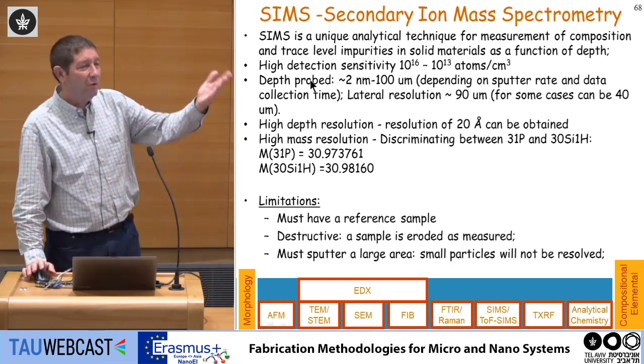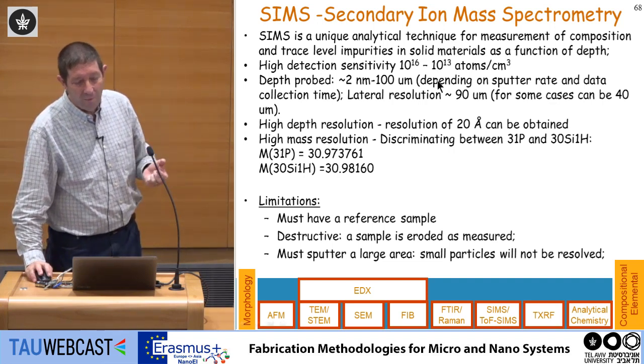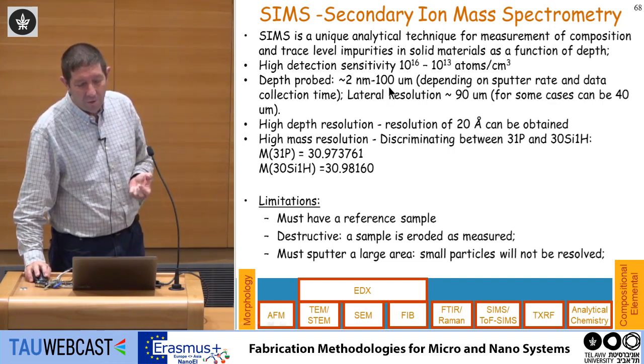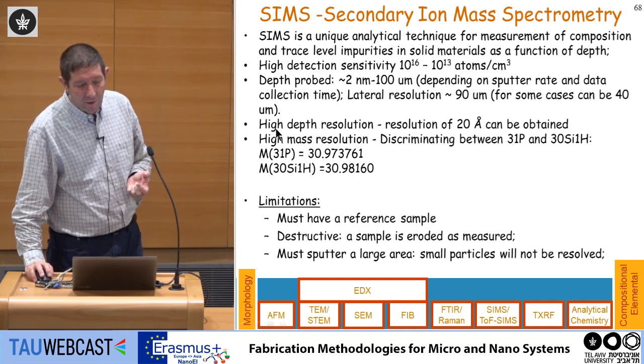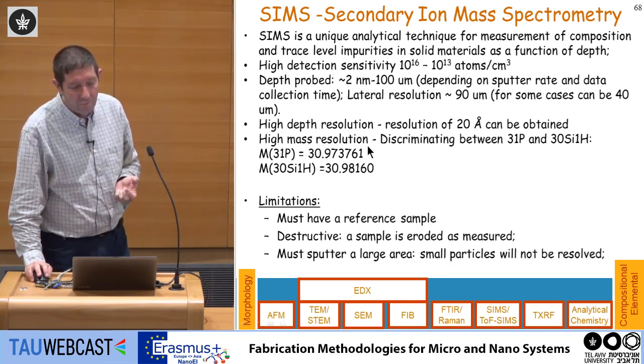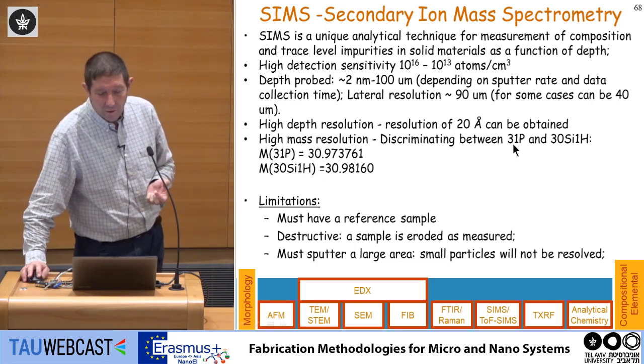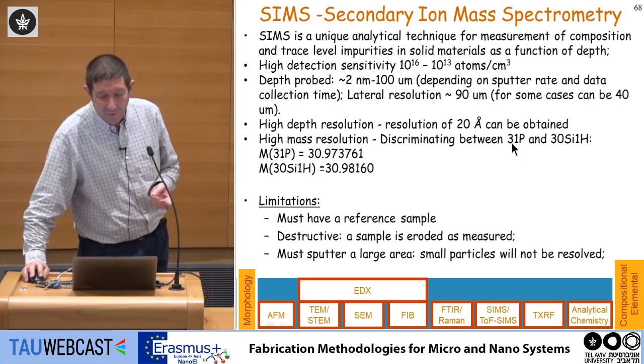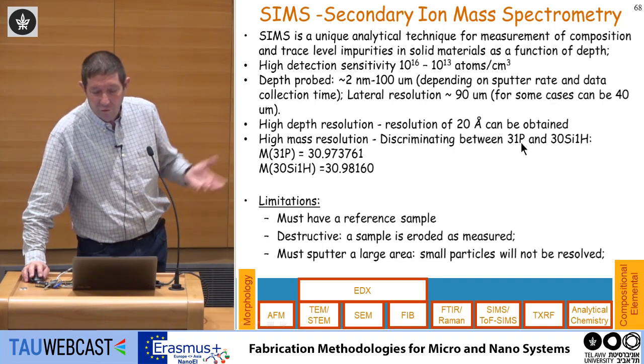It depends on my etching rate and my depth resolution. It can be 2 nanometers to 100 microns, and it has very high depth resolution, down to 2 nanometers. In high mass resolution, I can separate between phosphorus 31